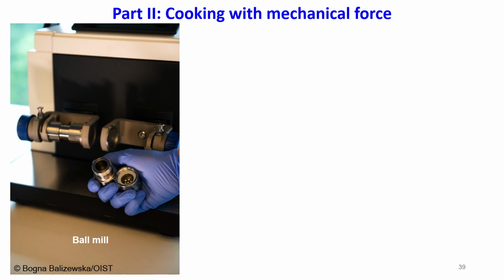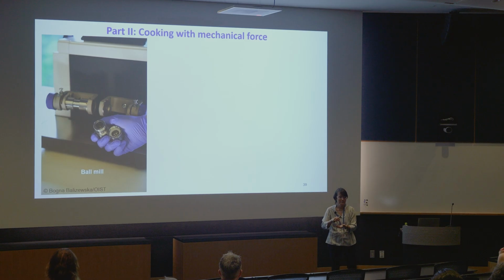So in a jar, you put your reagents, maybe a drop of solvent to help mixing, and one or several balls. Then you close the jar, then you fix it here in these arms, and the instrument starts shaking from side to side at a high frequency, 30 Hertz, for example. That's what we usually use. And the balls inside, they fly around because there is some headspace, and they hit the walls, create a significant impact, and that grinds the whole reaction mixture and enables very fine mixing.